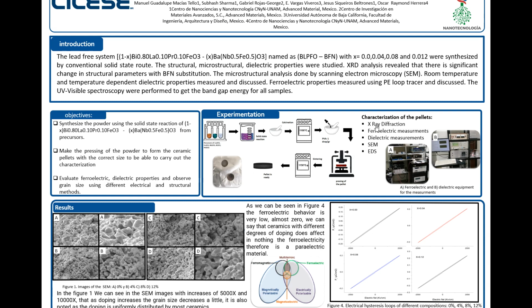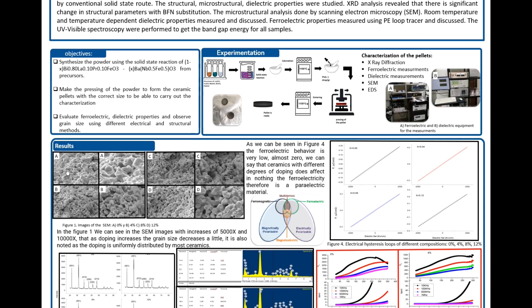The characterization for the pellets that we use is XRD diffraction, ferroelectric measurements, dielectric measurements, SEM and EDS. As we can observe, this is the equipment for the ferroelectric measurements and this is the equipment for the dielectric measurements. In the SEM images, we can observe at the beginning the 0%, 4%, 8%, and 12%. We can see this grain is different from the 4 and 8. This is for the doping. The grain is decreased. This image is for 5000x and this is for 10,000x, and it's the same for all of the compositions.